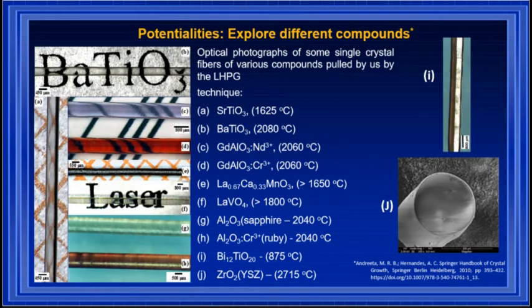The reason we think laser pedestal growth is a very good technique to produce templates to combine crystals and ceramics can be seen in this slide, where we show several crystals that were produced by this technique. We can see that we have a wide range of melting temperatures, and we can produce even crystals without congruent melting. In this way, you can search for the best lattice mismatch to combine with your ceramics.